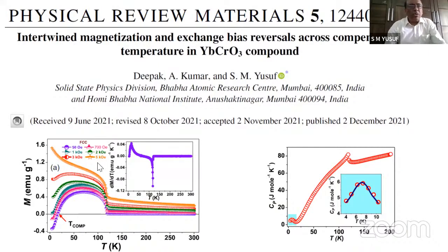Yeah. So here again you see magnetization as a function of temperature. What you see, the compensation temperature, negative magnetization, but with increasing field, it remains positive. Specifically, it also shows the kink at the magnetic ordering temperature and also at the compensation temperature, and where the compensation temperature we show here in the inset.